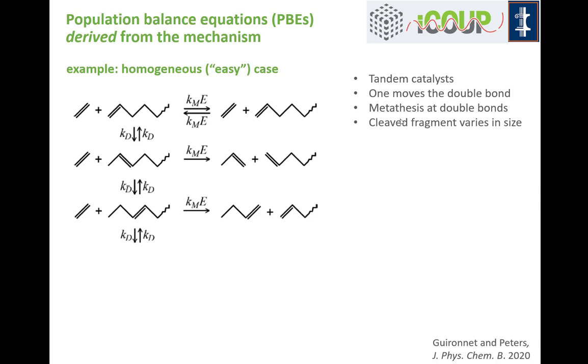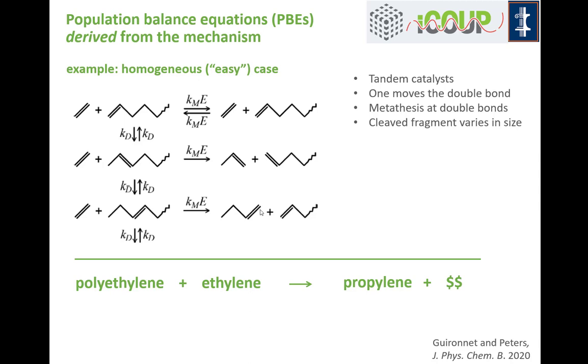Let's begin to develop population balance equations by considering an easy case — homogeneous chemistry. In 2020, thinking about a hypothetical situation where you have a homogeneous catalyst that allows double bonds on a Phillips-type polyethylene to migrate inward along the backbone of the polyethylene chain. If you combine that catalyst with an olefin metathesis catalyst and excess ethylene, then when the double bond has moved into the interior of the chain, ethenolysis will cleave that chain and cut off a fragment from somewhere near the end.